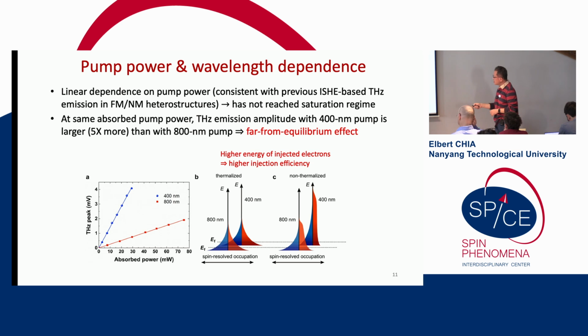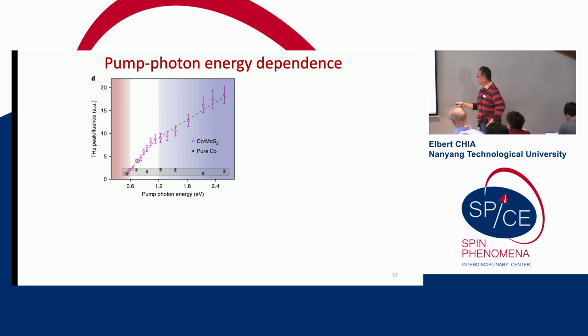But just taking data at these two wavelengths is not sufficient. So we did a systematic measurement where we pump from 0.5 electron volts to about 2.5 electron volts. And so you can see that at below about 0.6 eV, the Terahertz emission that we got is similar to that from cobalt. And then as we increase the pump photon energy, there's a linear increase. And then at about 1.2 eV, suddenly there's a change in slope.